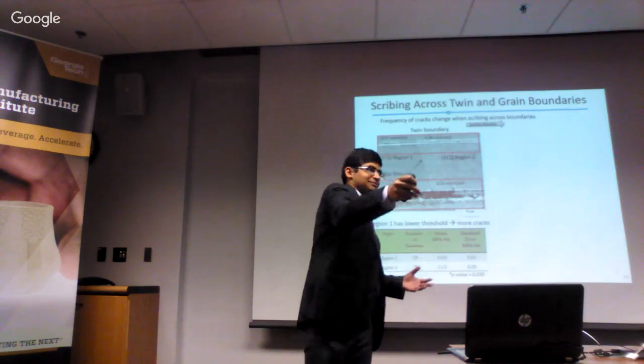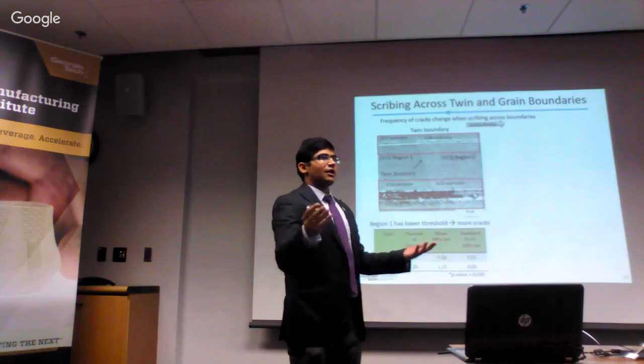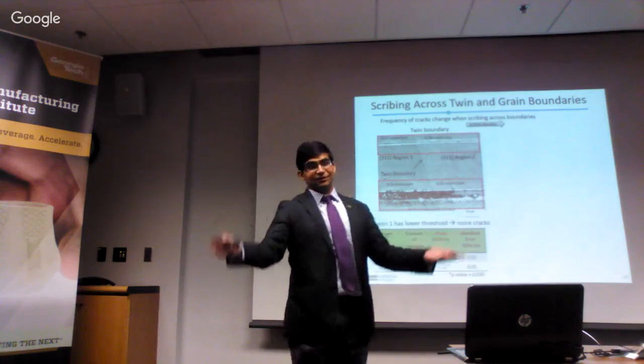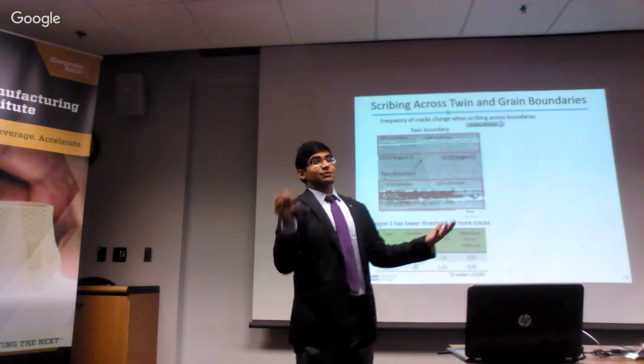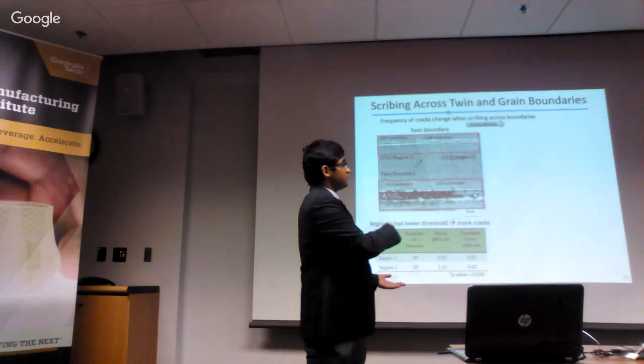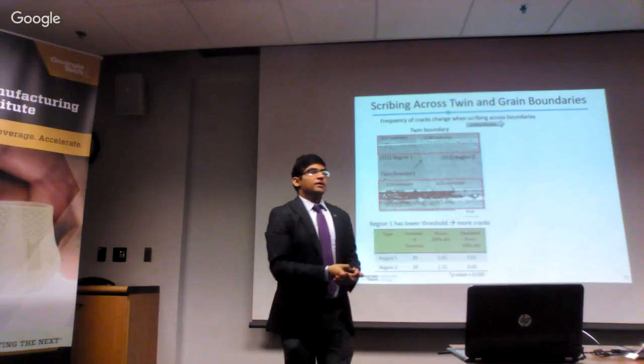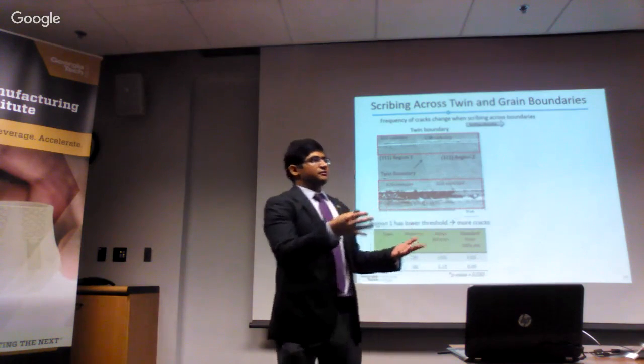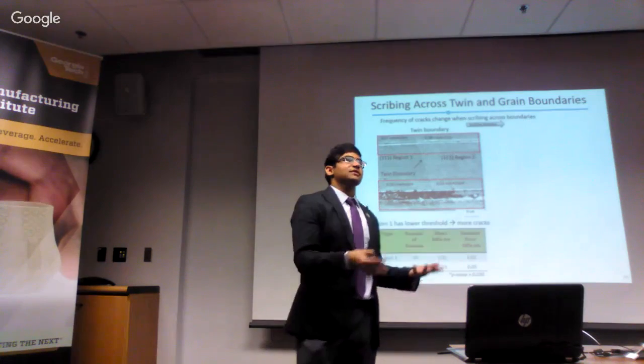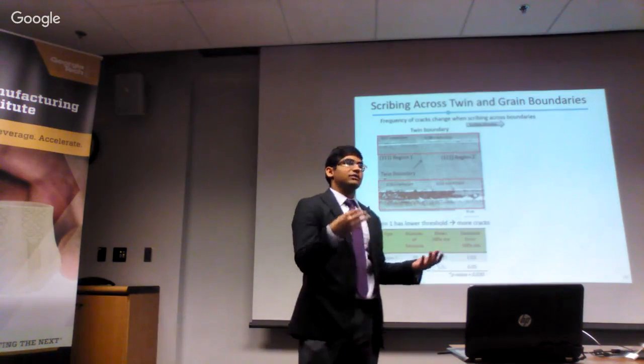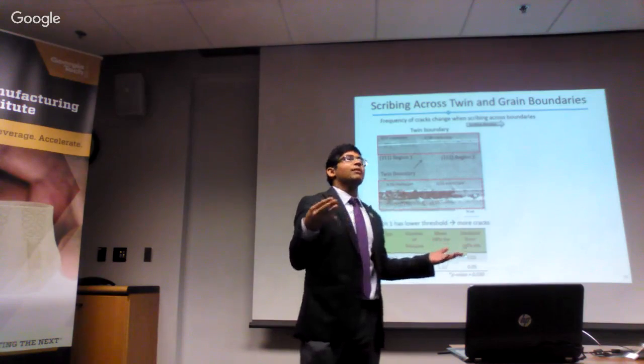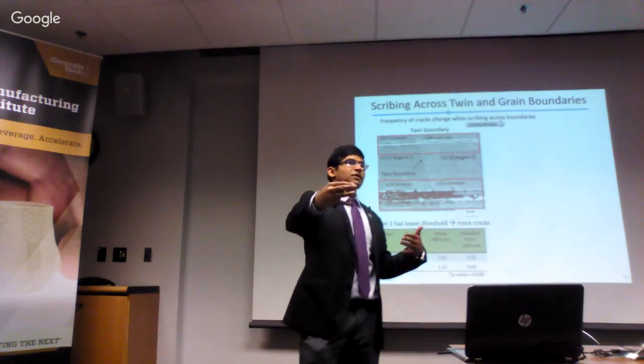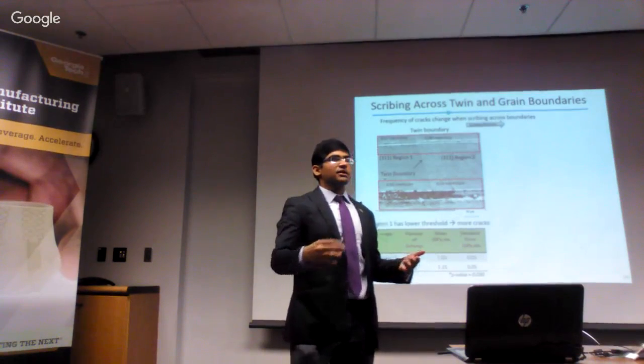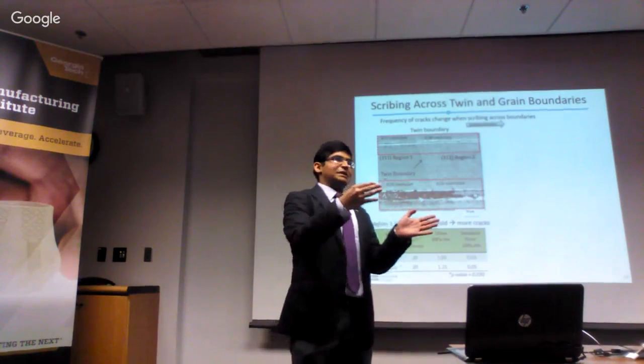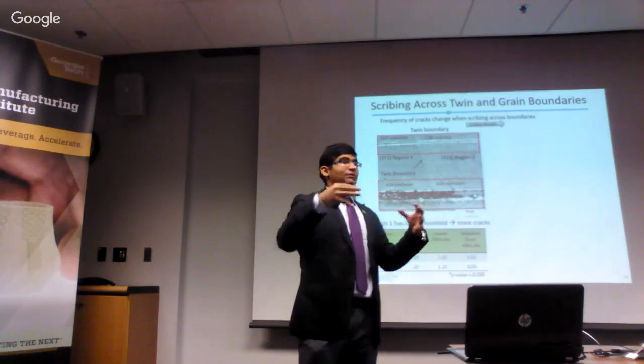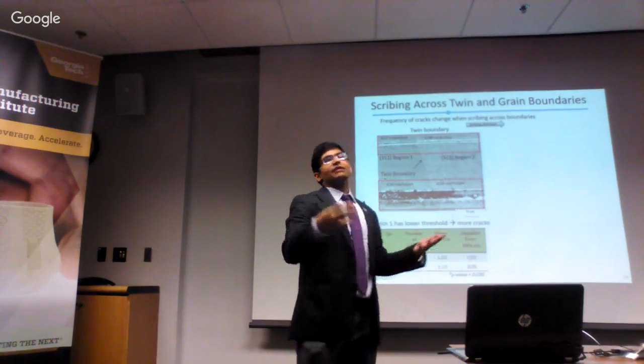which means region 1 had a lower threshold to fracture. Less energy has to be pumped in. That's what fracture toughness is. How much energy going into the material before the fracture occurs. So less energy has to be pumped in before fracture occurs in region 1 compared to region 2. Now, why this is happening is most likely, which we are hypothesizing, that the material properties across the boundary are different, because any boundary in multi-crystalline silicon is a discontinuity, where things like dislocations can pile up, inclusions can come and just stay there because they cannot cross that boundary during the solidification process at different stages of solidification.